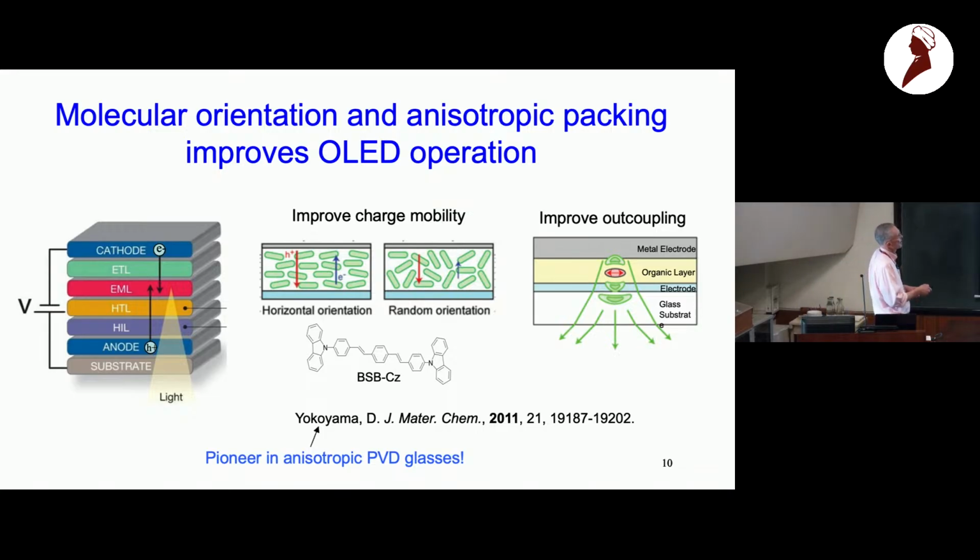Okay, so let's think about the difference between having these rod-like molecules in this arrangement or in a random arrangement. Just empirically, it turns out you get much higher charge mobility in this arrangement by more than an order of magnitude. But the more important factor for OLEDs is just a sort of a trivial geometric thing.